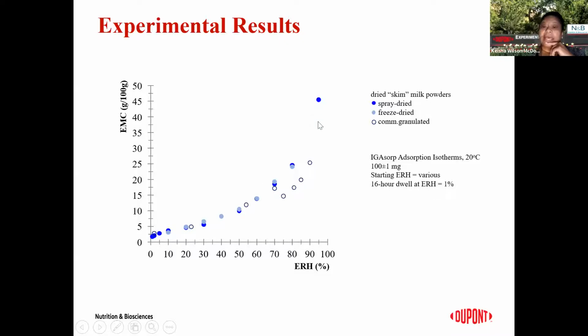One of the things that's well published in milk isotherms of skim milk is a discontinuity in the moisture absorption isotherm due to lactose crystallization. We did not see that in the original powders that we spray dried, and most likely, because we know where the crystallization is supposed to happen, it's because our data is not fine enough that we didn't see it in the smaller powders that were produced via spray or freeze drying. But in the commercial granulated isotherms, we were able to see that discontinuity that is well published due to lactose